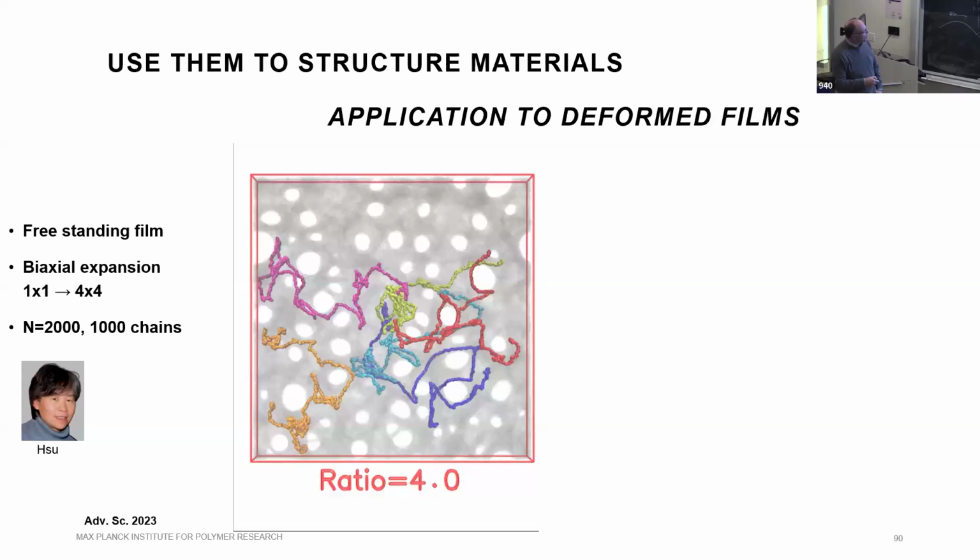Then you see that many holes form. And of course, what you would expect for a standard material is that these holes grow and coagulate, so that you have one big hole, because that would minimize the surface tension. But here it looks like they are stable, and they are stable because here the chains, and these are just 6 chains shown, are so long that they expand over many different holes.